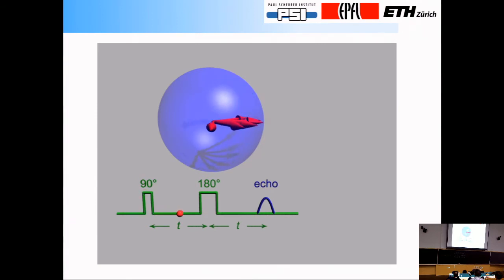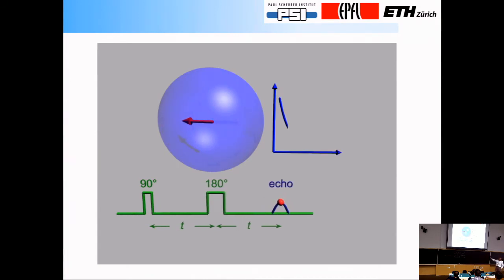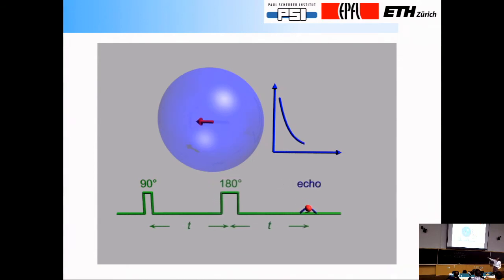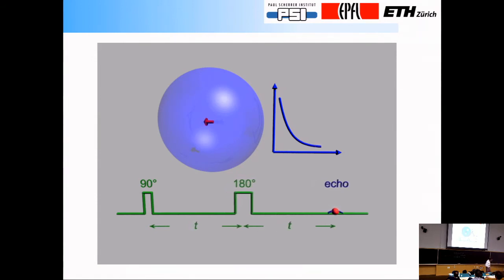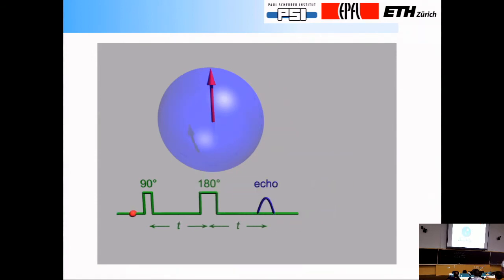Then you have a coherent superposition of up and down. Then you apply what's called a refocusing pulse. And then if you wait an exact time which is equal to the distance between the pi over 2 and pi pulses, you get what's known as a spin echo. So you can then vary this time, plot up that echo curve, and the decay of the echo gives you directly the decoherence time. In other words, how good is this as a controllable quantum mechanical element?